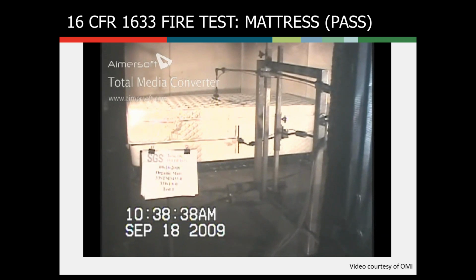These will go again for 70 seconds and 50 seconds. And in order to pass, the mattress set must not exceed a peak heat release rate of 200 kilowatts at any time during the 30-minute test. And the total heat release for the first 10 minutes must not exceed 15 megajoules. So what they're doing there is they're really trying to make sure that the initial ignition of the mattress with the burners does not create a quick flashover scenario.